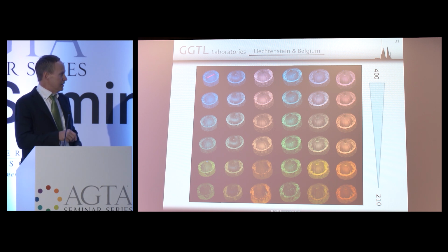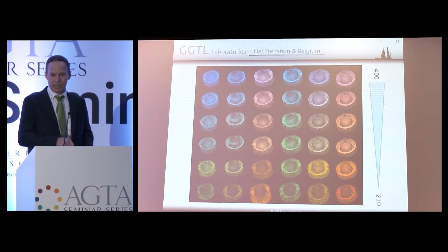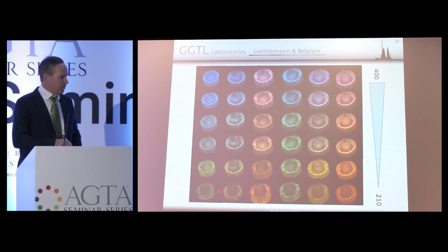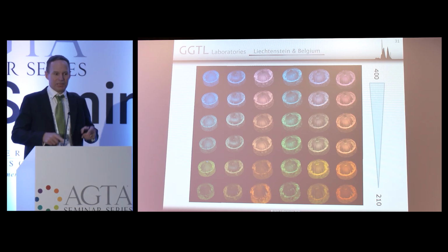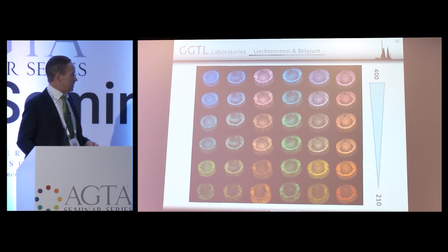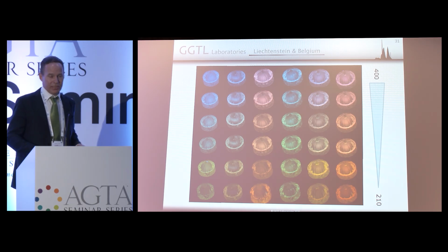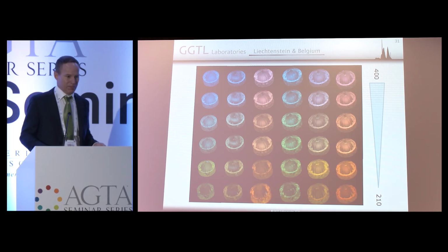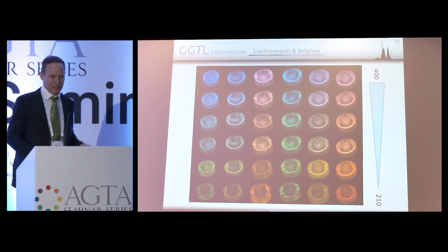You see a blue fluorescing stone, and it fluoresces yellow or green under deep UV, there's something wrong. A natural diamond would fluoresce blue down here. So the sequence would be blue, blue, yellow, yellow, blue, blue. Okay? So these sequences, that's what we use at the lab to distinguish them visually. We don't even have to take a spectrum. You usually do at the end, but you know, you see that and you know, oh, that's a CVD.